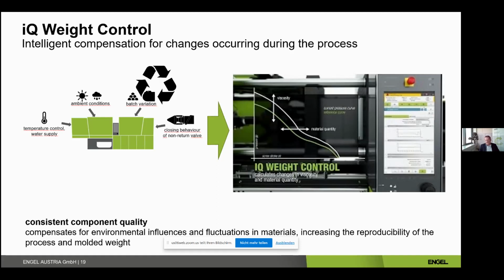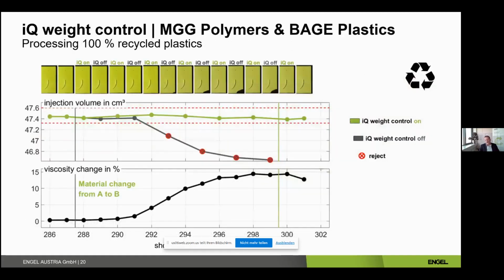So the shot weight is influenced by the viscosity most, and this is a problem for recycling material. The shot weight is also influenced by the closing behavior of the non-return valve, by different temperatures and ambient conditions. And all these conditions get controlled, let's say so, by the IQ weight control system. And this figure shows how it works.